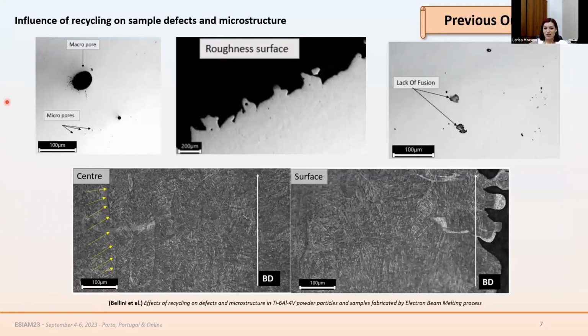We also investigated the defects inside the components produced with the electron beam melting process, and we saw no particular difference between the three kinds of components. All of the components investigated showed the classical defects typical of the electron beam melting process, which are macropores, tiny porosity, surface roughness, and of course lack of fusion. And all of these defects are mainly due to the process parameters and not to the recycling processes.